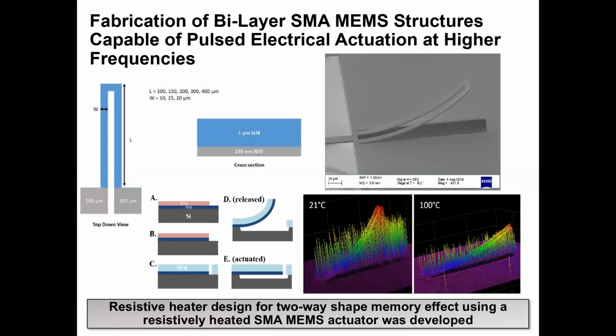So this is looking at the fabrication of the bilayer MEMS structures capable of pulse actuation at higher frequencies. The figure on the left-hand side shows how this bilayer actuator was built into a double beam resistor pattern, which would be suitable for inducing the shape memory effect by Joule heating. So beams with varied widths and lengths were fabricated using different designs on the mask plate. NiTi was patterned using photoresist and ion milling. And then SU8 was spun onto the wafer to a thickness of 1 micron and then patterned with an additional